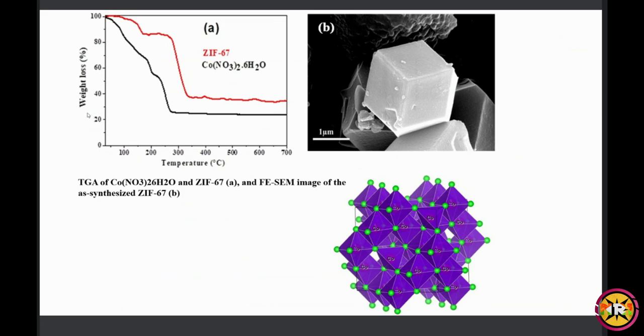So for SCS, solution combustion synthesis, I have taken normal cobalt nitrate salt as an oxidizer, and glycine as a fuel. For ZIF-67, basically I have synthesized first ZIF-67 from cobalt nitrate and imidazole moiety, and ZIF-67 is nothing other than the cobalt tetrahedrally bridged with the imidazole moiety.